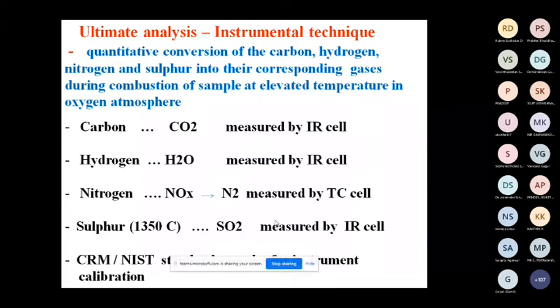These instruments are calibrated using certified reference materials or NIST standard materials. So all the instruments are calibrated for carbon, hydrogen, nitrogen, sulfur. By using that calibrated instrument, you can measure the ultimate analysis, carbon, hydrogen, nitrogen, sulfur, by instrumental technique. As I told you earlier, in the earlier method it would take 1 or 2 days per sample. Now, within half an hour, 30 minutes, you can complete carbon, hydrogen, nitrogen, sulfur per sample using instrumental technique. That is a very big advantage with the instrumental technique.